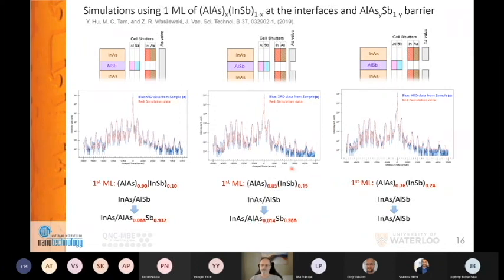So this is, with that technique, and you can consider those diffraction ramps as a Fourier transform of the actual structure to some degree, and the angular range which we are looking at, which is not quite 3 degrees, will translate into a resolution in real space of about 20 angstrom. So this is really not looking at monolayer-like accuracy. Nevertheless, in combination with the in situ measurements I described, it does give us, I think, a fair view into where the arsenic is. But there are many other things happening at those interfaces.